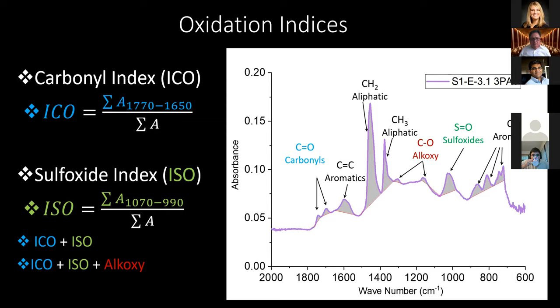So the carbonyl index takes the areas under those peaks that are highlighted that have the carbon bonds: you have the carbonyls, the aromatics, the aliphatics, the alkoxy, and the aromatics. The sulfoxide index will analyze those sulfoxide peaks from 1070 to 990. The addition of those peaks can provide you those indices that can be used for comparison.